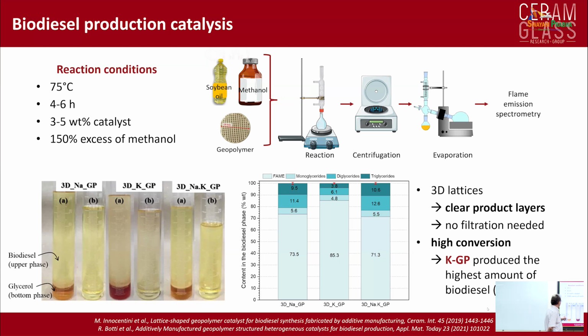We worked with colleagues from Brazil for this work, and we used soybean oil as a source of triglycerides. And you can see that the system worked. We were able to generate biodiesel plus glycerol. And the yield is certainly below the yield that one expects from commercially available approaches. But as I mentioned, we didn't try to further optimize the reaction. We wanted to demonstrate that you can use this approach.